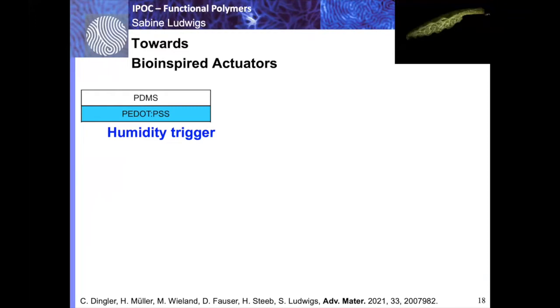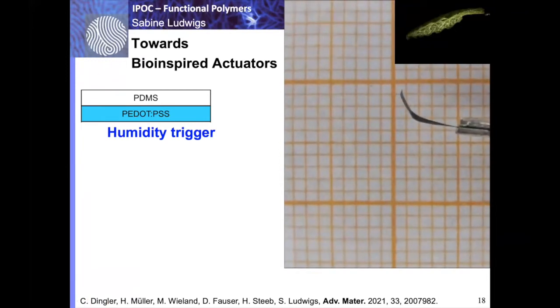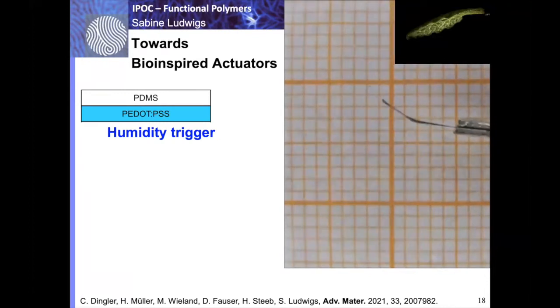So we thought of the easiest possible geometry, and that's a bilayer. So we combined PEDOT:PSS layers, in this case they are thicker. So this is PEDOT:PSS about 5 micrometer, and the PDMS is bigger with 50 micrometers. So we made it on PDMS, which is essentially a passive layer, and PEDOT:PSS is an active layer which can react to the relative humidity. And that's one of these experiments, and you see it looks very similar to the leaf of the botanic garden. So this simple bilayer actuator can actually change its shape from being elongated and then being curled. So it really curls in here.